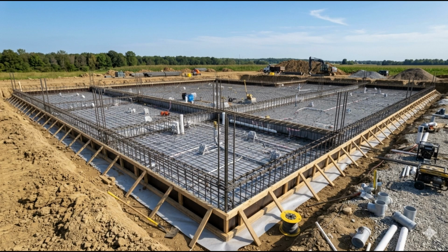He specified that steel fixing was to be supervised by a competent site engineer, who was to carry out inspections before and after the placing of each layer of reinforcement, and to confirm in writing that the reinforcement was correctly placed, the cover was within tolerance, and the spacers were in position before any concrete was placed. The tolerance on bar spacing was specified as plus or minus 15 mm from the design spacing, which was consistent with BS 8500 requirements. The tolerance on cover was plus 10 mm, minus 0 mm, meaning that less than the specified cover was never acceptable, but some excess cover was permissible.